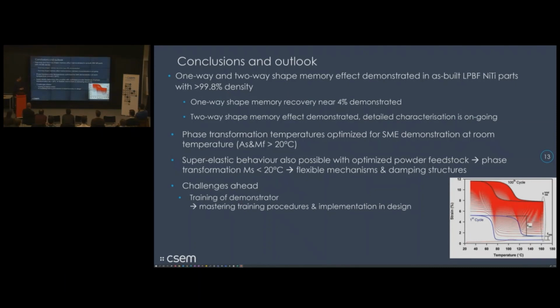There are some challenges ahead. There is one peculiarity of shape memory alloys in the training. So during the training, actually, this is a strain as a function of temperature. So during first cycle, there is a certain maximum strain that you achieve, but during the training, this strain increases, and this is very important to take into account in designing, for example, two-way shape memory actuation. It needs to be taken into the design at the very early stage, and also it brings certain aspects in designing of future actuators. So it's important to master the training procedures, it's absolutely necessary, and its implementation in design.